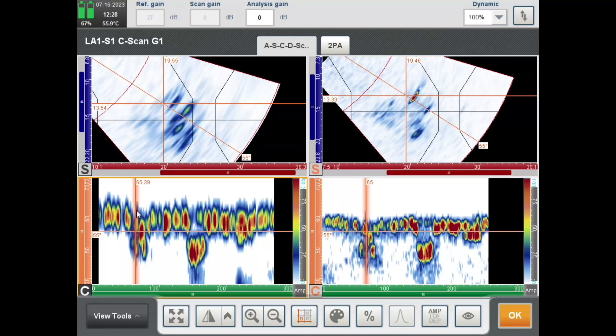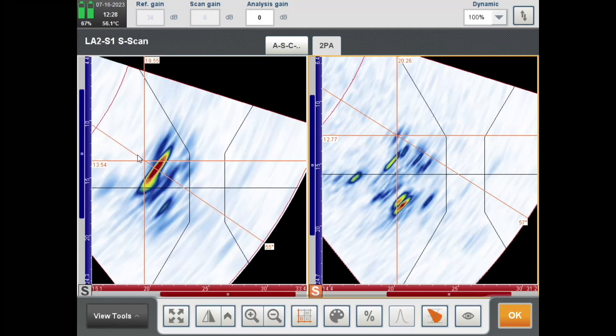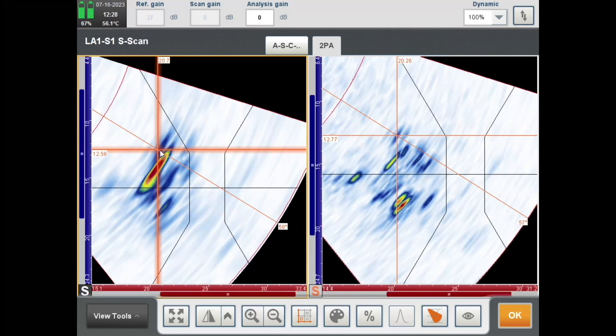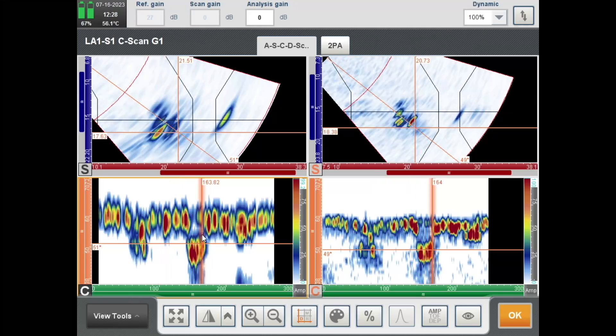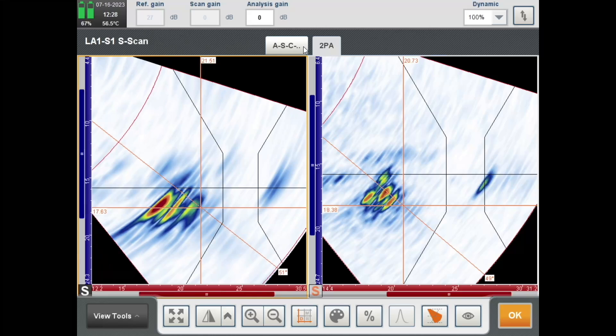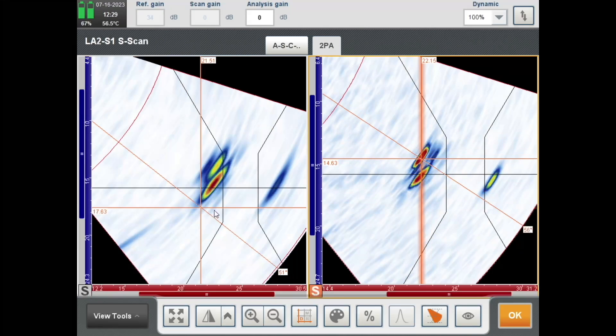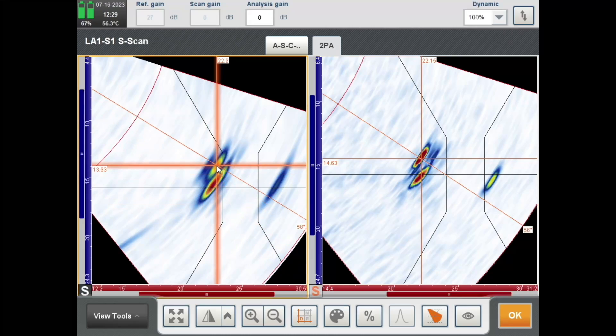The first flaw on this plate is slag. The 10 MHz is pretty obvious — it's much easier to see all the little facets. Moving to the second flaw, it's a crack, and it doesn't present exactly like you'd expect because flaws are weird. The third flaw is lack of penetration. This one's fairly obvious, and again it's just easier to get a size on it using the 10 MHz.